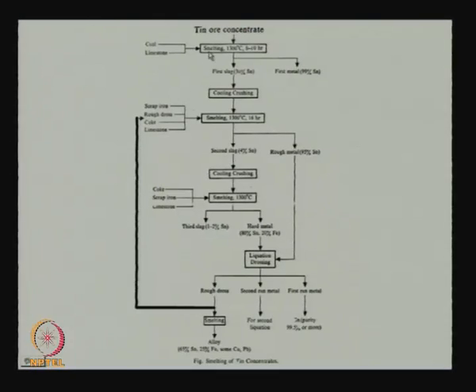Then we smelt, say at 1300 degrees for 8 to 10 hours, we put coal, we add limestone to make a slag, because the limestone will combine with gangue, which would have SiO2, and produce a fluid slag. In that fluid slag 3% SnO2 will dissolve.